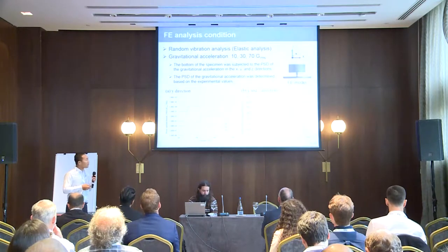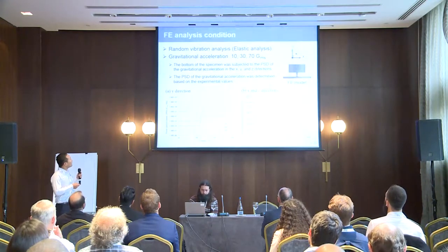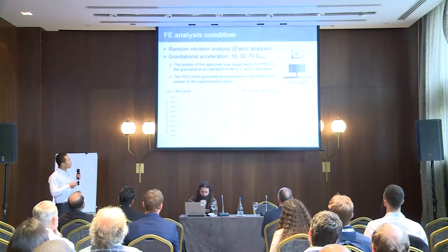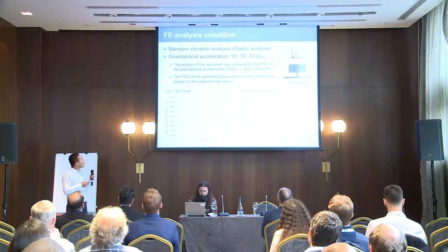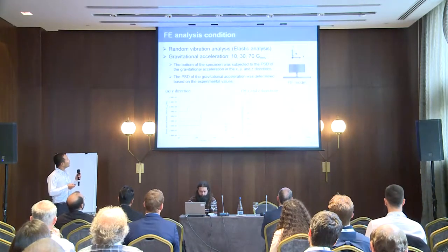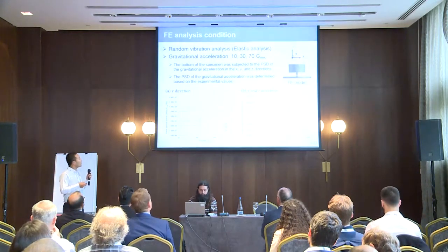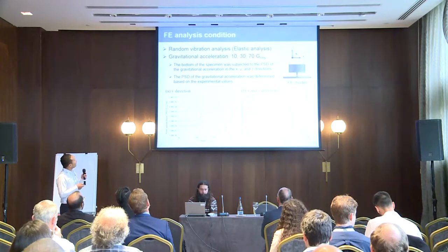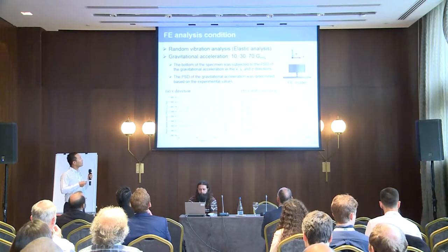We also conducted finite element analysis. This slide shows the conditions. We conducted random vibration analysis using elastic analysis at three conditions: 10, 30, and 70 GRMS. This is the finite element model. The bottom of the specimen was subjected to the power spectral density (PSD) of the gravitational acceleration in the X, Y, and Z directions, and the PSD was determined based on the experimental values.